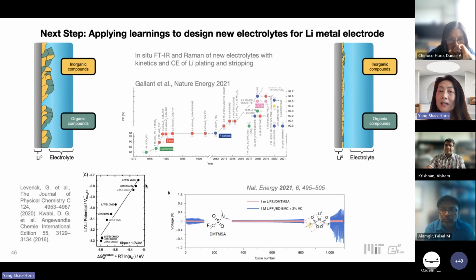And this essentially would change the thermodynamics and kinetics of reduction of the solvent, reduction of anions that can form, for example, very different SEIs, either organic or inorganic SEIs, which underlie the stability of lithium stripping and plating and influence the morphology. Right. So essentially, our current thinking is that if you have an electrolyte that controls the right reduction of organic solvent and anions, developing a more inorganic passivating layer, one can render a higher efficiency.